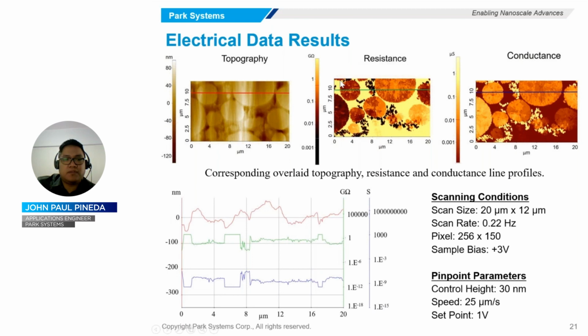So the darker colors on the conductance image represent areas with lower surface conductivity, while brighter colors represent higher conductivity. So in comparison of the topography and conductance images, it demonstrates that circular plateaus with higher height have higher conductance when compared to low-lying areas.